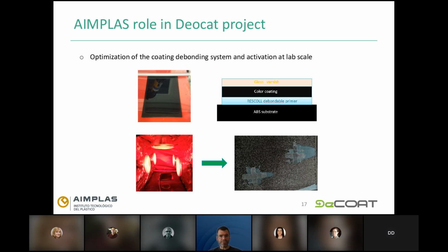In the next presentation, my colleagues will be able to provide more details on this debondable primer. And afterwards, the painting and color coatings and varnishes were applied onto this special primer. After heating activation by means of infrared lamps, we were able to assess the debonding capabilities of these primers, so that the paint layers can easily be removed from the plastic substrate.